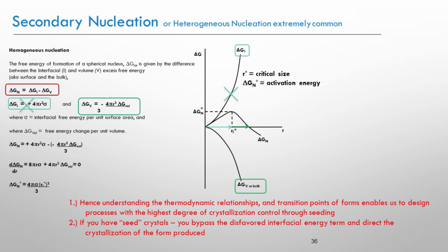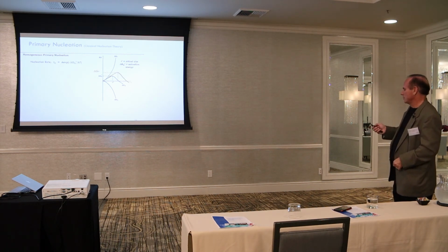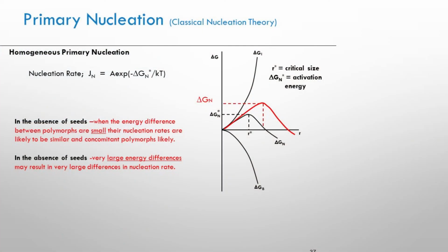And if you do the inverse of that, which is nucleation rate, basically the bigger the energy difference between the crystalline forms, the higher this nucleation activation energy.